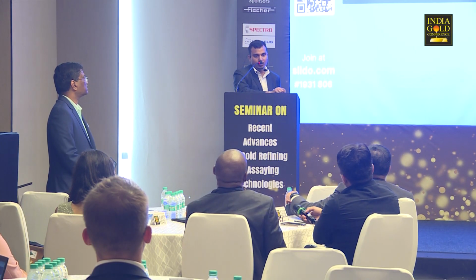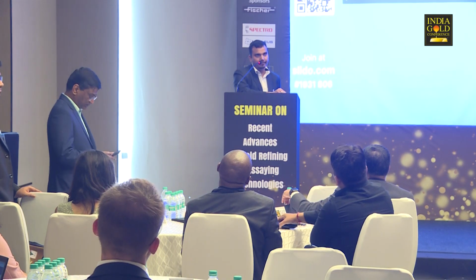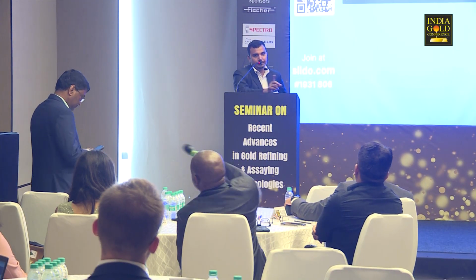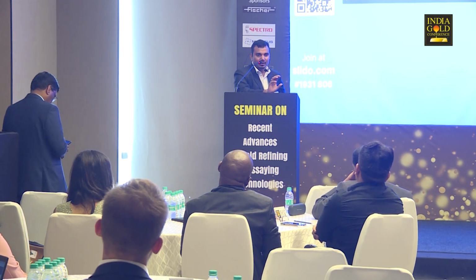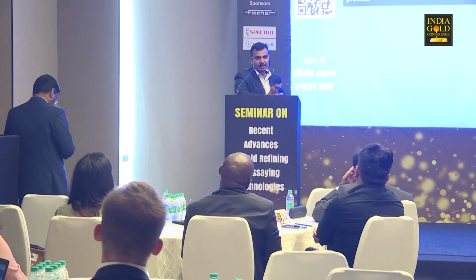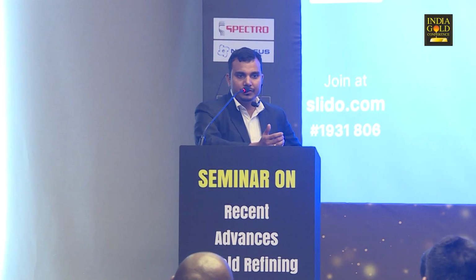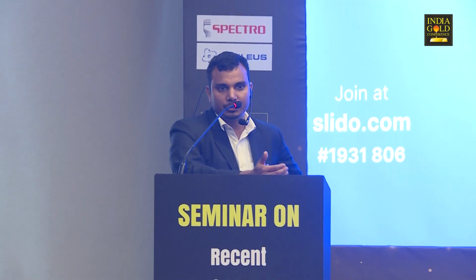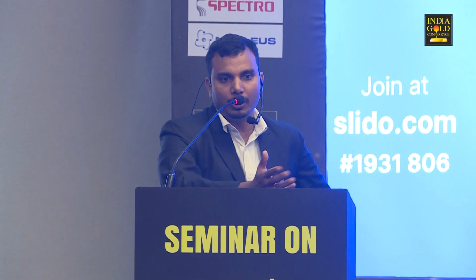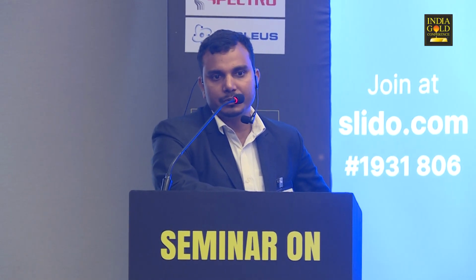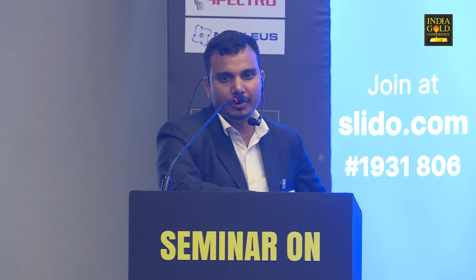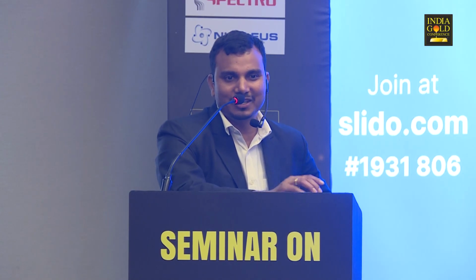Okay. So one is this heterogeneity that is there. But first, let me clarify the copper part. Copper I used as collector because I had very small mass. So I needed some collector, otherwise it will not separate from slag. But if you have larger volume, you don't need to use copper collector. Now, second part is sampling. In our case, we sample from the liquid. So we have ways to take a sample from the molten state itself, so that the homogeneity is preserved, so that we'll know how much gold or whatever is the composition. So it's not very complicated, but we do that. At least at lab scale, it's not complicated.